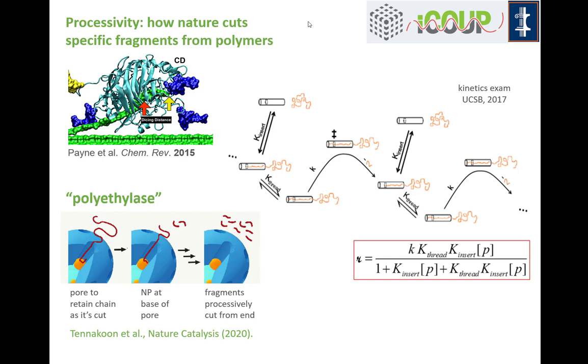Can we design a system that would do this synthetically for polyethylene? This was the inspiration in the early days of iCOUP work. The idea is to have an active site off-center in a long narrow pore. The polymer, if it has an enthalpy attraction to that pore, should load in, reptate into position, cut a small fragment away, and then go back through this processive cycle over and over again.